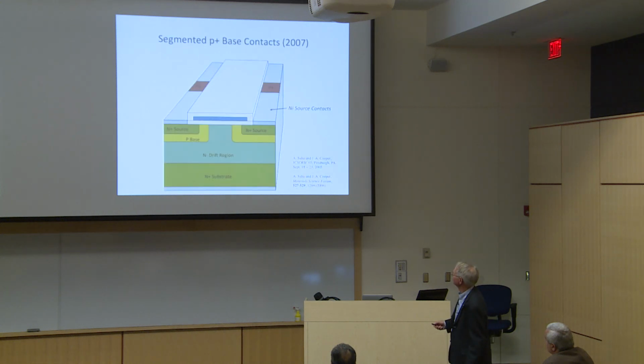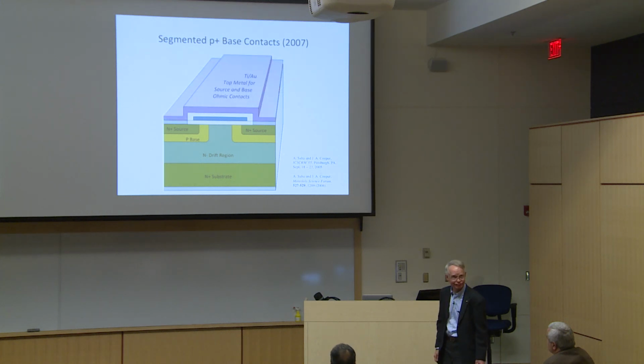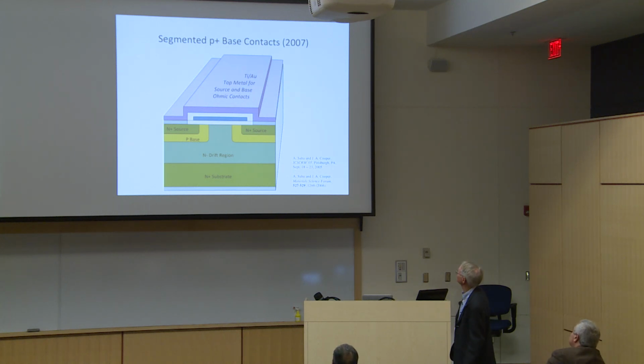So what we did was, as you go back along these fingers, we dropped in P+ contacts periodically. And then that was enough. So we have this region here. We've got a P+ contact. We have a different metal to make contact to it. And then the whole thing is covered with top metal. And this carries all of the high currents that the device has to carry. So it reduces some of that resistance as well.